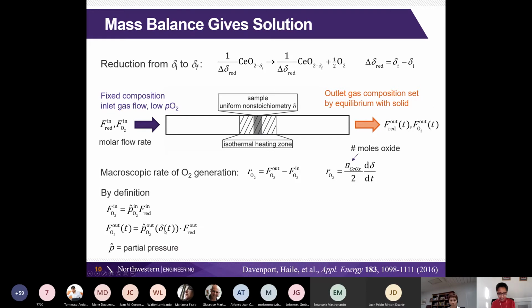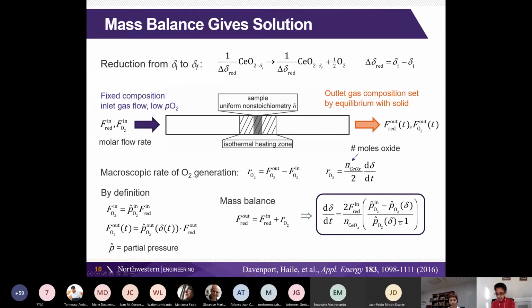This is the quantity that we'd like to know. We don't know what it is, but if it is in equilibrium with the gas, then we know its relationship to the oxygen partial pressure through our thermodynamic measurements of the material. We have another mass balance step, which says that the total flow rate coming out is just the flow rate that was in plus the oxygen content that we generated through this reduction reaction. So these two are actually independent, and we put it all together, and we have this very simple expression for the change in non-stoichiometry, which depends on the flow rate of gas coming in divided by the number of moles of material that we put into our reactor, and then this thermodynamic term.